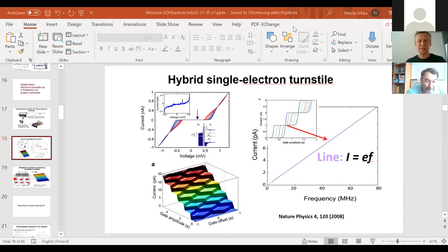Okay, can you share some details about the resistors nanofabrication? Which material do you use? In which voltage range do they behave linearly? Which resistance values can you reach? Also, a reference would be helpful. Okay, this is a good practical question. In many experiments, we use just very standard copper metal or gold palladium. We do it by just the standard electron beam evaporation. These are, of course, very linear in essentially any voltage range, but then of course rather low resistance. So recently we have also used chromium.